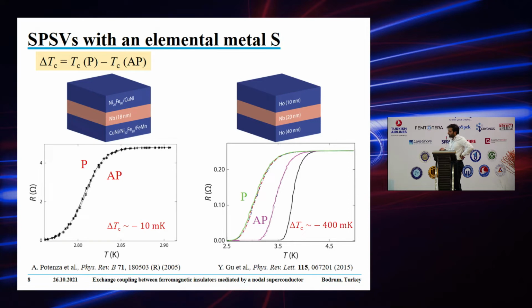There has been work done in the literature to prove this, way before I started working on spin valves. One of the first papers sandwiched an elemental metal superconductor between two ferromagnets. In this case, as you can see, the delta TC, which in this talk I will define as the TC difference between the parallel and antiparallel states, was of the order of a few tens of millikelvin.